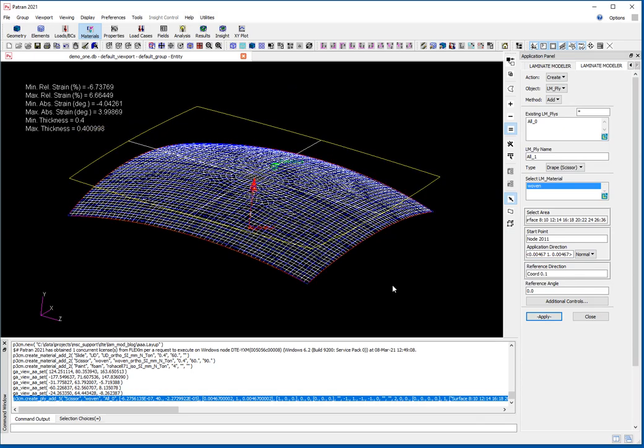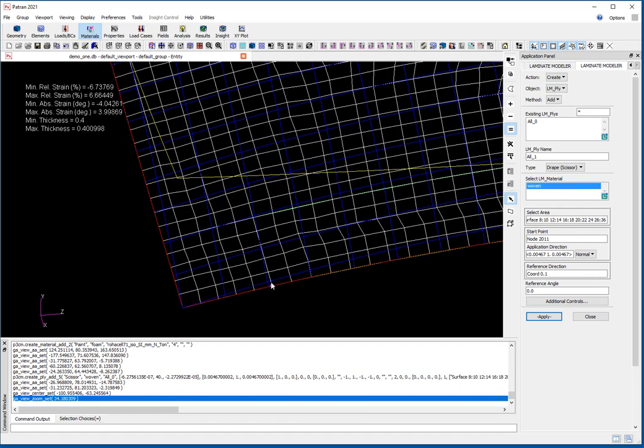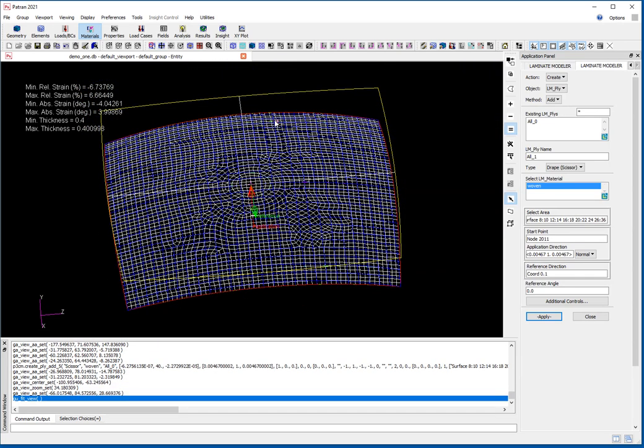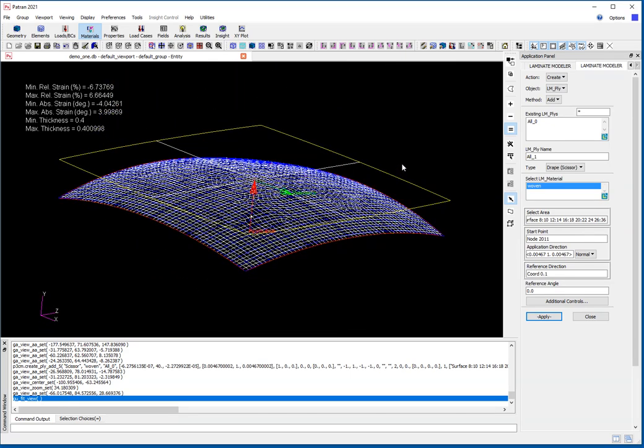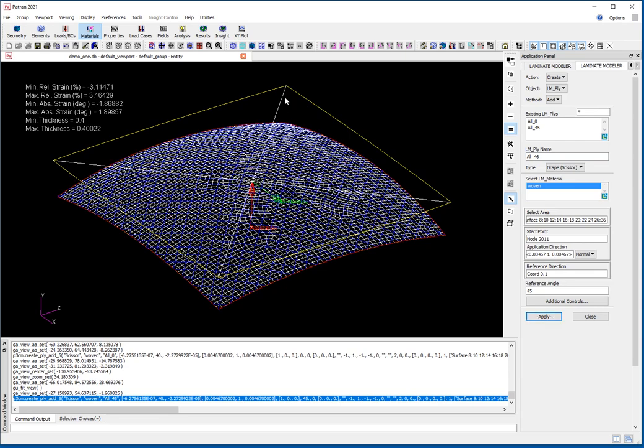When I hit apply, it goes through very quickly and does two things. It generates an underlying blue grid that shows how the warp and weft directions change as the draping happens. But it also gives me this yellow outline of the flat pattern — showing what shape I'd have to cut the fabric in order to drape it on there. I'm then going to make one at 45 degrees by changing the reference angle to 45 and applying again. The crosshairs on the flat pattern now show warp and weft, which I can use in nesting software to understand how to cut it from a roll of fabric. Those are my two plies: 0 and 45 encapsulating the whole structure.